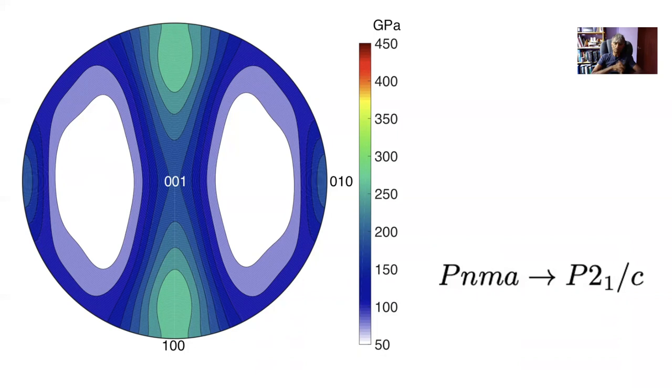So you might wonder, you know, if shear is so easy, then why is cementite hard? And there's a really interesting reason: when you elastically strain the cementite, because it's an anisotropic structure, the space group symmetry changes to monoclinic P21/C. And from the point of view of bonding, that strengthens the covalent component of bonding, and therefore the crystal actually becomes stiffer. Okay, so that's the elastic modulus of cementite.